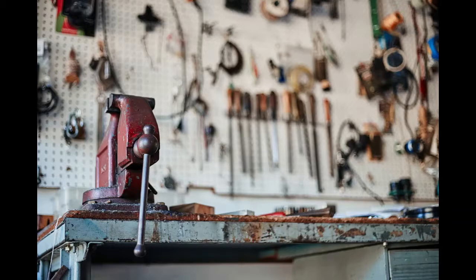For a larger quantity, and when it is required to be very soft, pack the steel with cast iron, lathe or planer, chips, in an iron box, as follows, having at least 1/2 or 3/4 inch in depth of chips in the bottom of the box. Put in a layer of steel, then more chips to fill the spaces between the steel, and also the 1/2 or 3/4 inch space between the sides of box and steel, then more steel. And lastly, at least 1 inch in depth of chips, well rammed down on top of steel.